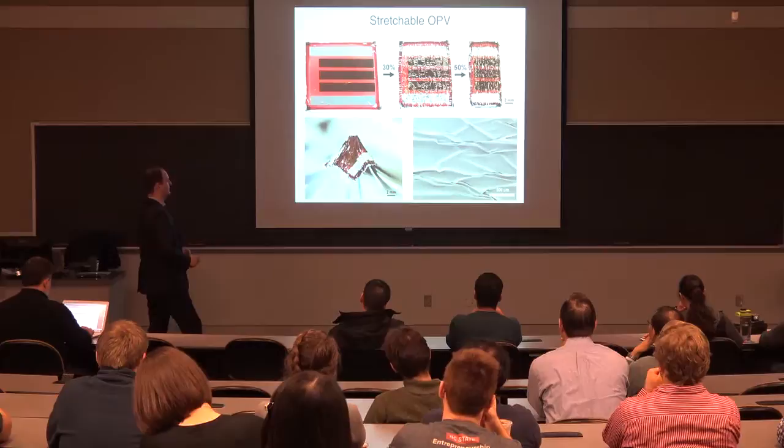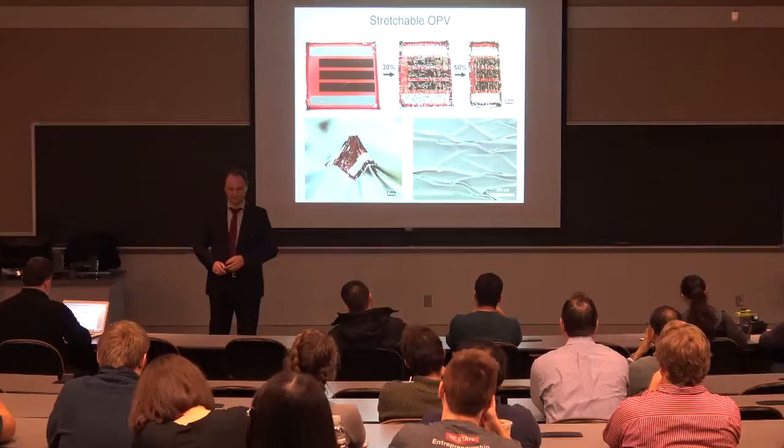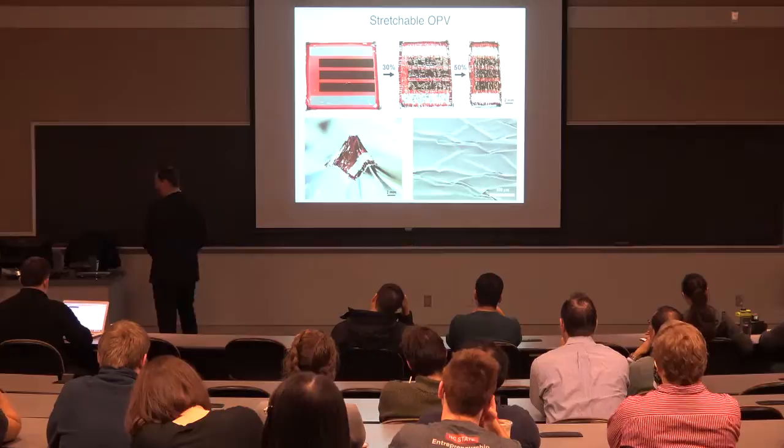It's not really sinusoidal. If you look at it in the SEM, you'll see that you have valleys that are virtually uncompressed, and then the sharp high aspect ratio wrinkles, which are called ridge wrinkles. Those form if you have a high level of pre-strain in the elastic foundation, and then you snap the hard membrane on top. Of course, you can do that in two dimensions, and then you have 2D deformable electronics, if you have to know.